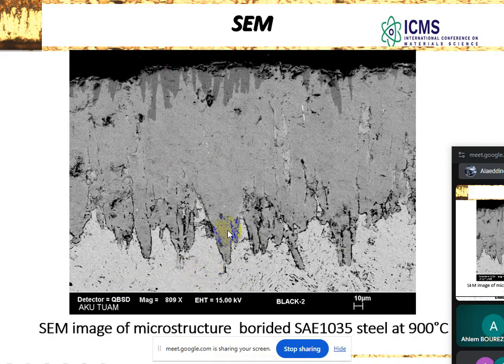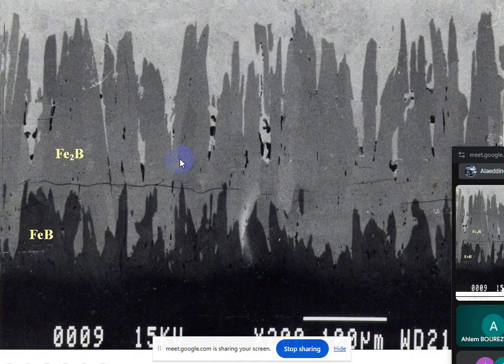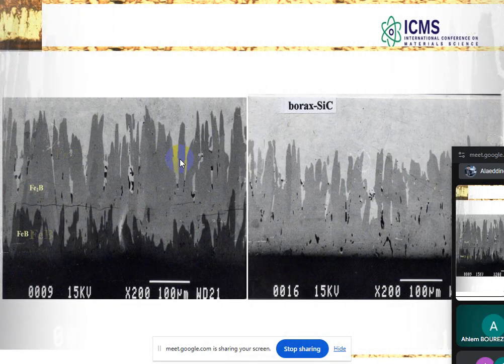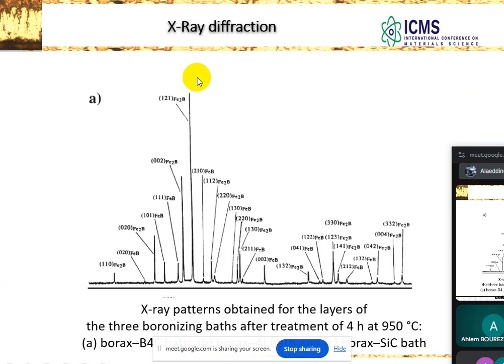This treatment is for carbon steel at 900 degrees Celsius. And for boron carbide, we have a double phase, iron 2 boride and iron boride. If you use only borax and silicon carbide, we have a monophase. We have only one phase, iron 2 boride. We don't have iron boride.